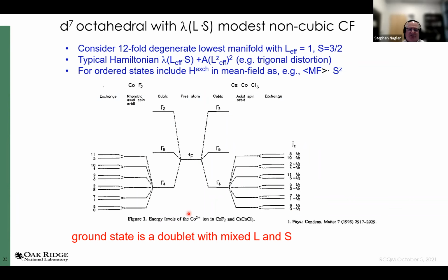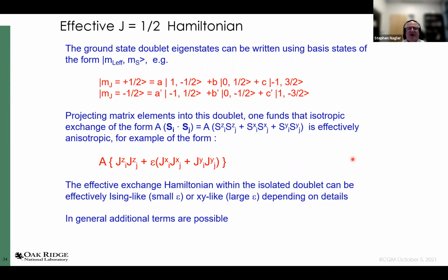And under those, with this other perturbative Hamiltonian, spin orbit coupling and some departure from cubicity looking like this, you end up with a set of 6 Kramers doublets. Again, the lowest lying state is a doublet, and it has mixed L and S. So in fact, it turns out in this case, I can write these states as some linear combination in terms of ML and MS, if you like, L and S type eigenstates, and they will look like this.